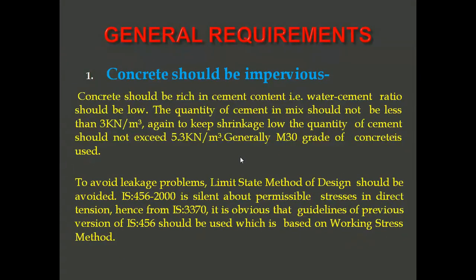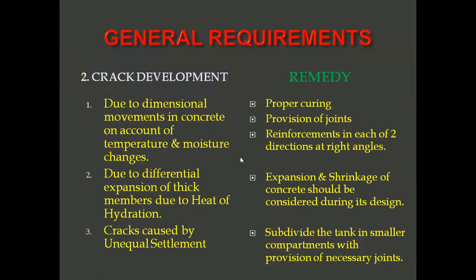Crack development may occur due to dimensional movement in concrete on account of temperature and moisture changes, due to differential expansion of thick members from heat of hydration, and due to unequal settlement of loads. In circular tanks, tangential stresses also need consideration. Remedial measures include proper curing, provision of joints, reinforcement in each of two directions at right angles, and consideration of expansion and shrinkage during design. Subdividing the tank into smaller compartments with provision of necessary joints is also recommended.